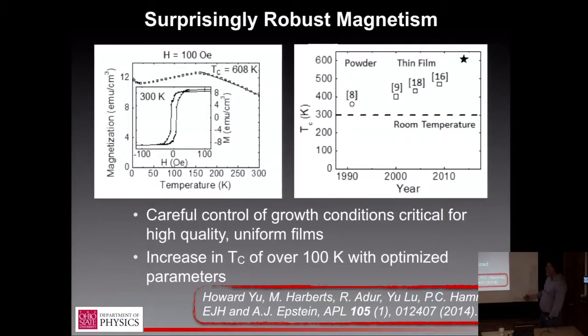And this is taken from this paper here, so these numbers are references to prior work. And you can see moving from the powder synthesis to the thin film CVD synthesis. And then this is the work of one of my students who's just graduated and moved to Intel, Megan Harberts. And there's no magic sauce here, this is basically, as I said, just a matter of being as careful and systematic as possible in mapping out the phase space and the control for the growth. And we had very nice properties in terms of DC magnetization.